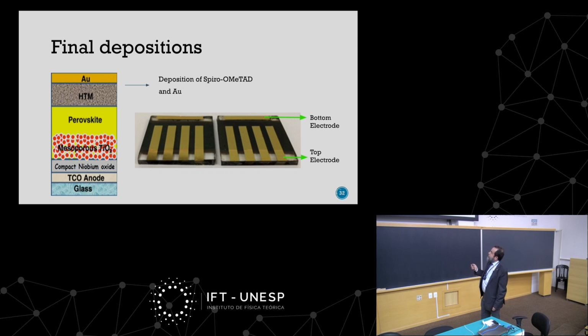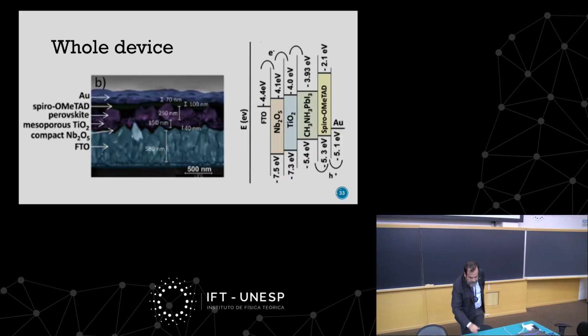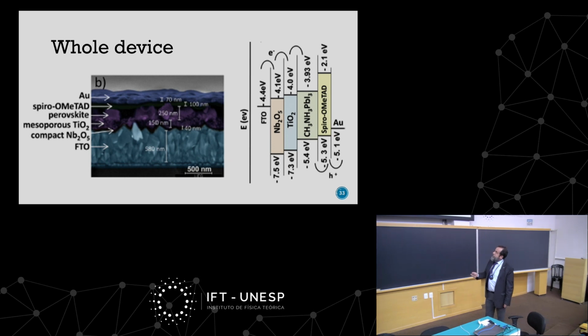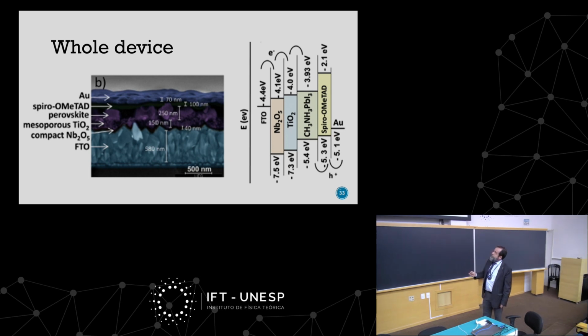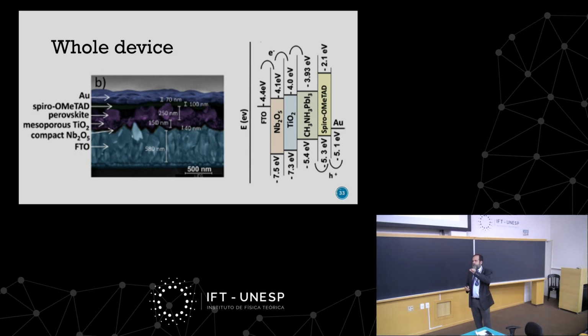And here is basically, again, the solar cell I have already shown you. This is the cell from the side. So here is basically the glass with the FTO. Okay, so here glass, FTO. And then you have the mesoporous layer, the perovskite, the spiro-OMeTAD, and gold. And these layers are typically, as you can see, 100 nanometers, 200 nanometers, really very thin. We use a very, very little amount of material.